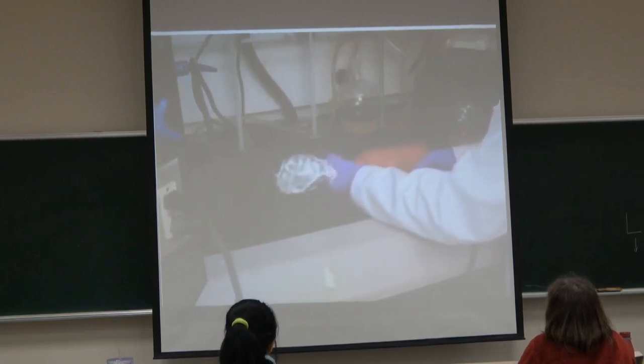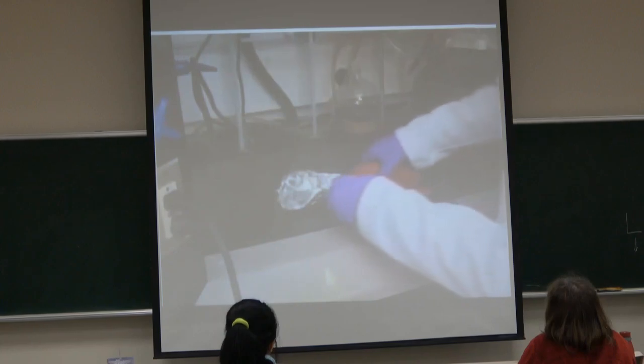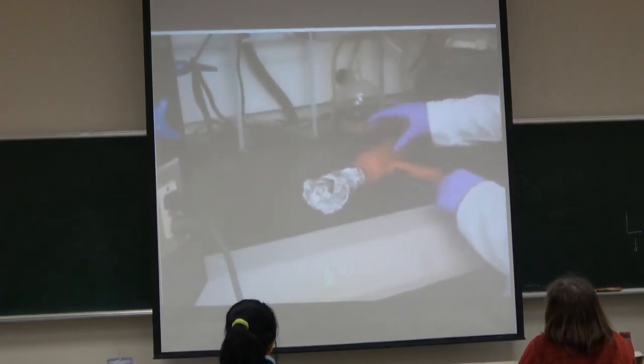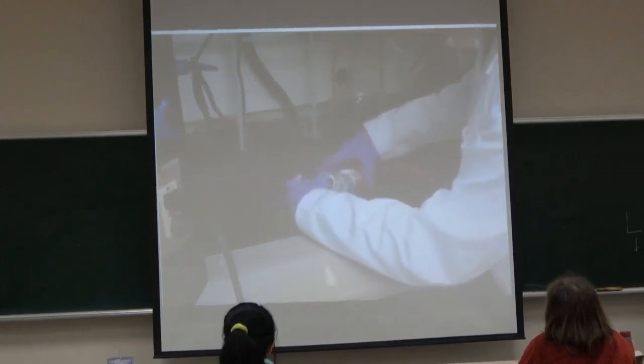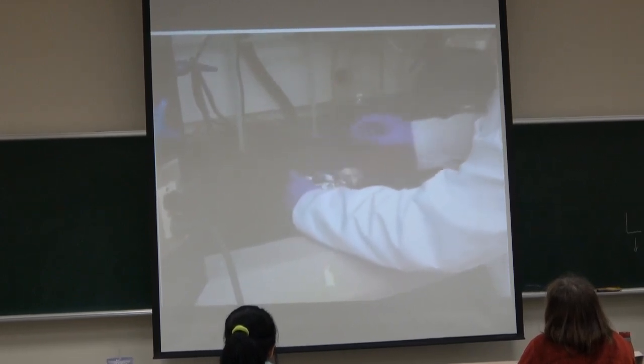Then wrap aluminum foil around the nozzle to form an enclosed oven. The slides will lie flat inside this oven for the annealing process. Be sure to leave a small opening in the foil so that you can watch the slides for color change as they anneal. Turn the hot air gun on high or to 450 degrees Celsius. Let heat for 30 minutes.